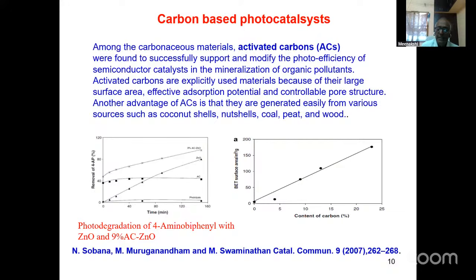So now let us see, actually we have used one or two carbon-based photocatalysts. Before going to biochar, we initially started in 2007 itself using activated carbon as a support material for the photocatalysts. So we have prepared activated carbon loaded zinc oxide and activated carbon TiO2 P25.